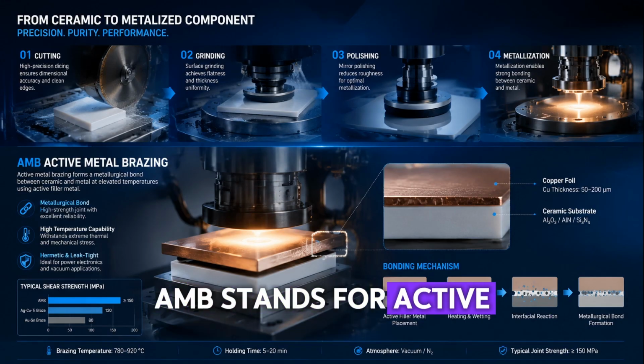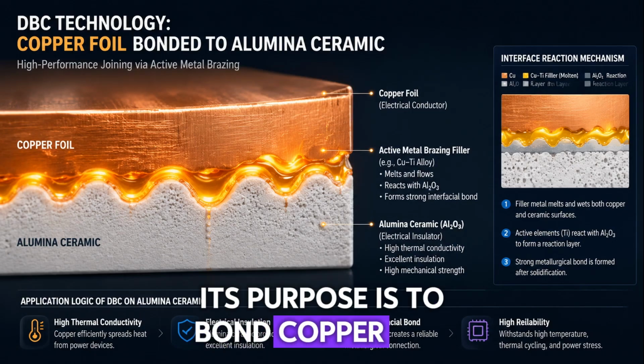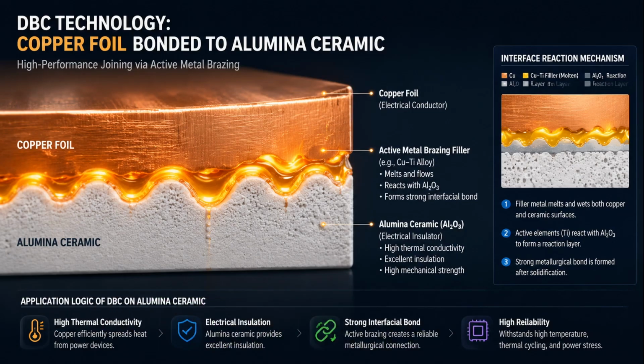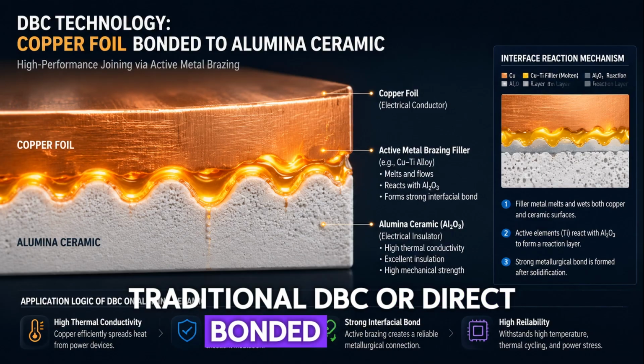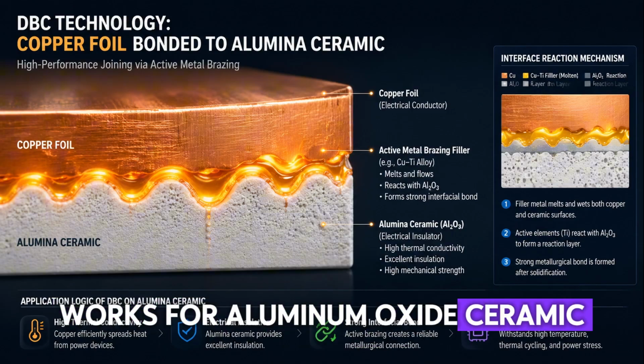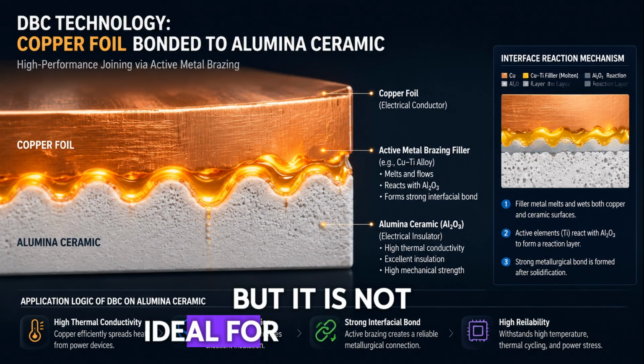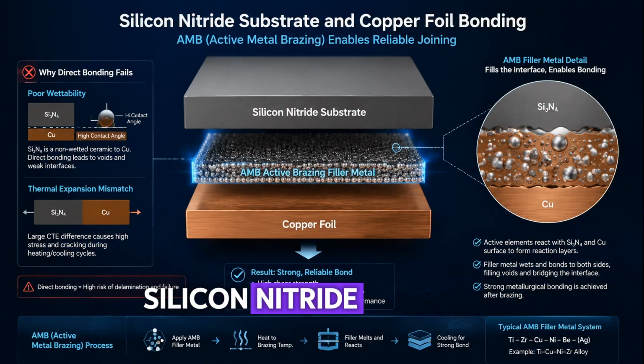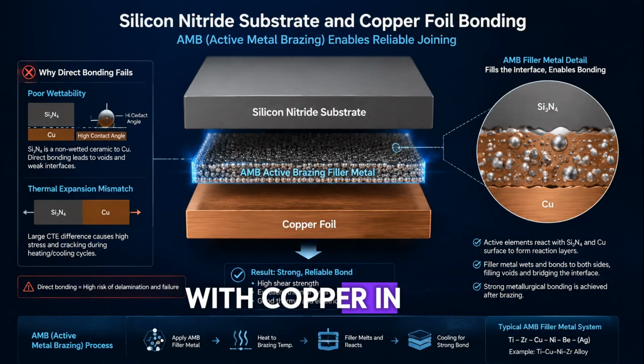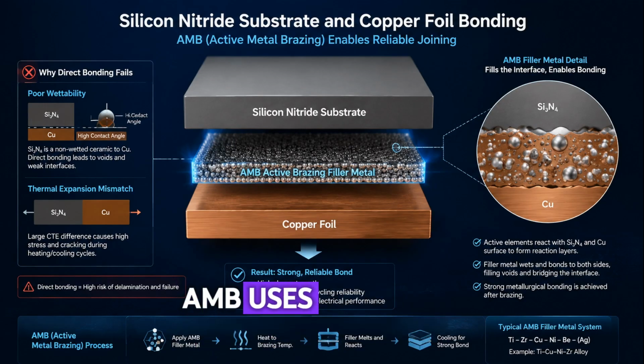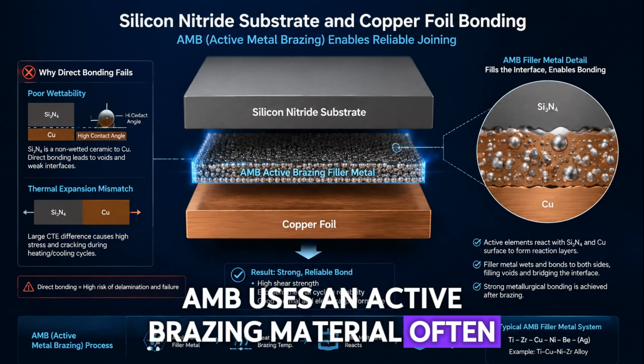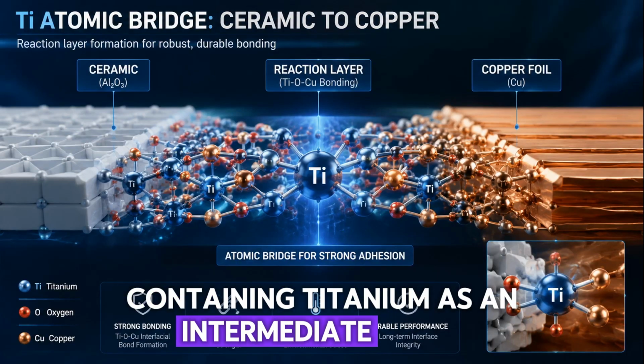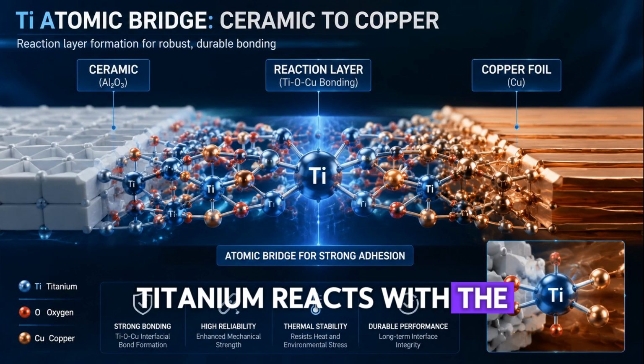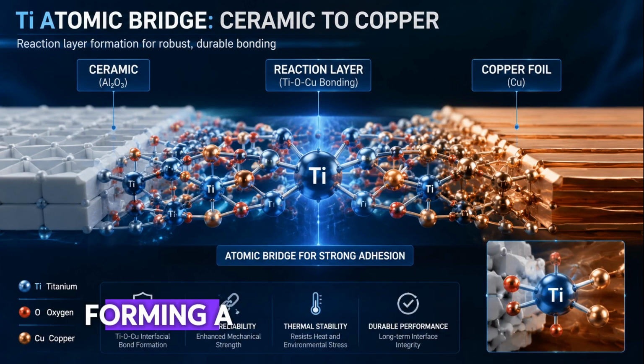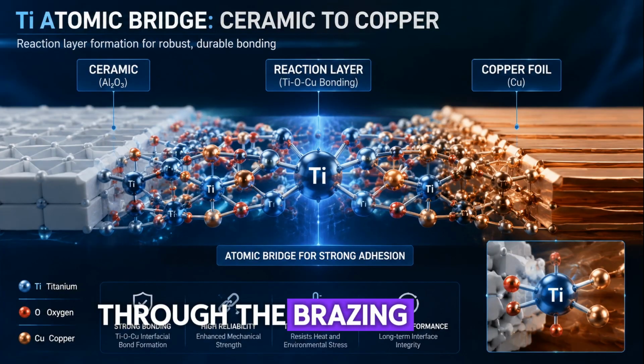AMB stands for active metal brazing. Its purpose is to bond copper foil firmly to the ceramic surface. Traditional DBC, or direct bonded copper, works for aluminum oxide ceramic, but it is not ideal for silicon nitride. Silicon nitride does not bond directly with copper in the same simple way. AMB uses an active brazing material, often containing titanium as an intermediate layer. Titanium reacts with the surface of silicon nitride, forming a stable bonding layer. The copper foil is then bonded through the brazing material.